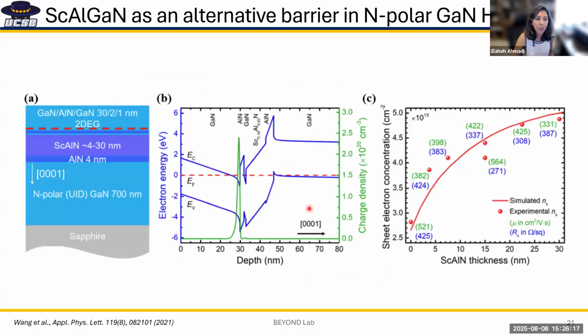When I was at Michigan, we did some preliminary work in collaboration with Professor Mi's group using scandium aluminum nitride as barrier, but this is of course not optimized. It was grown on sapphire directly by MBE, which means the dislocation density is very high. And it was not optimized at all, and so the mobilities are very poor, but still we could show that we can have this scandium aluminum nitride as the barrier.